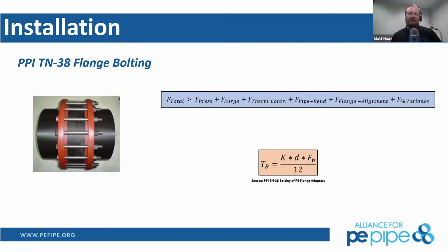So the technical note shows a logical breakdown that your total seating force, or sealing force rather, needs to overcome the sum of all the potential forces seen at that joint. So stacking forces can include pressurization, surge pressure forces, thermal contraction, bending forces, the alignment allowances, dimensional and material variance, and so on. So to simplify that stack up of forces, you can use the estimated equation for minimum operating bolt load, which is 7 times the working pressure rating times the ID area. So that cross-sectional area from the ID.